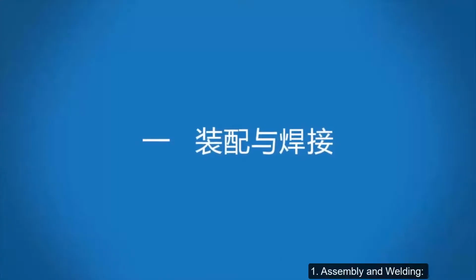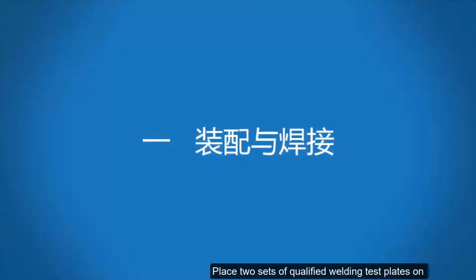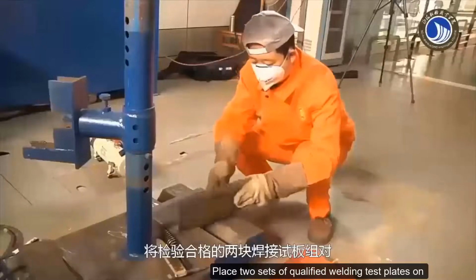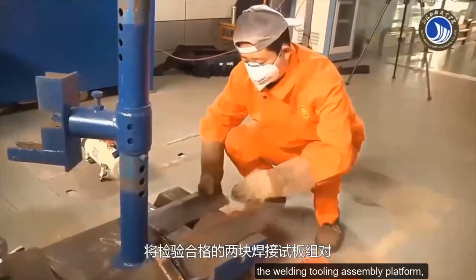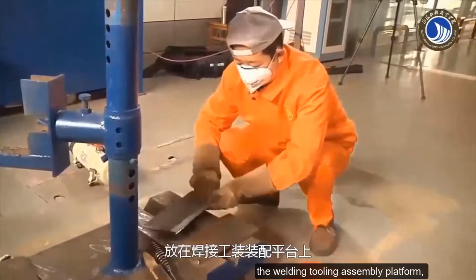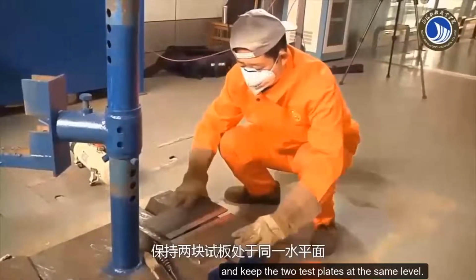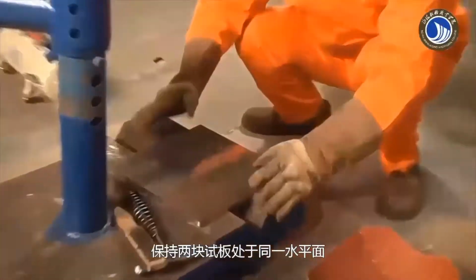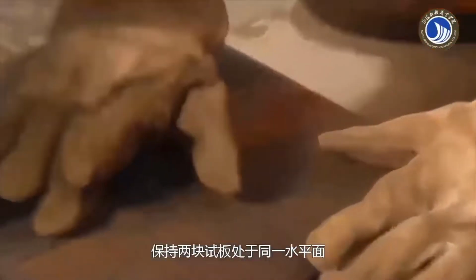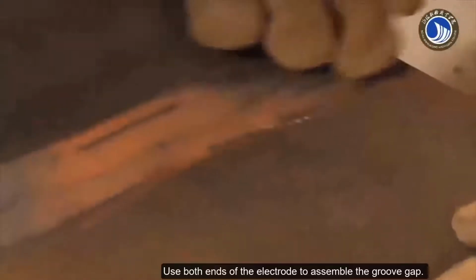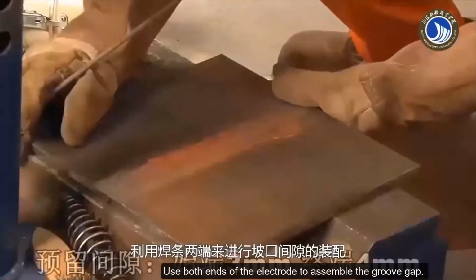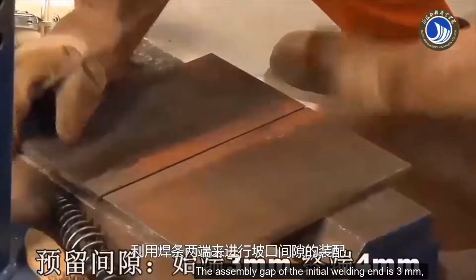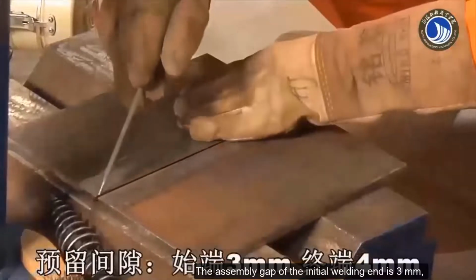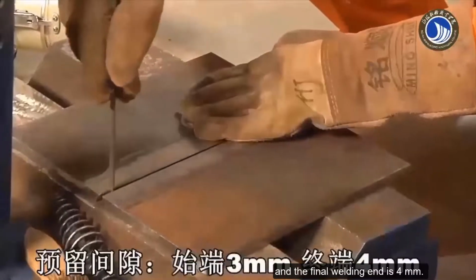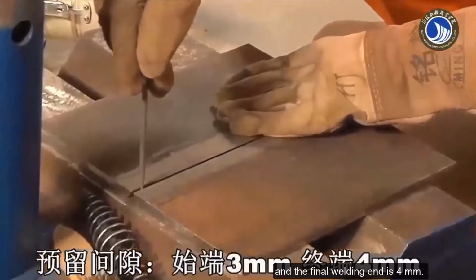1. Assembly and welding. Place 2 sets of qualified welding test plates on the welding tooling assembly platform, and keep the 2 test plates at the same level. Use both ends of the electrode to assemble the groove gap. The assembly gap of the initial welding end is 3 mm, and the final welding end is 4 mm.